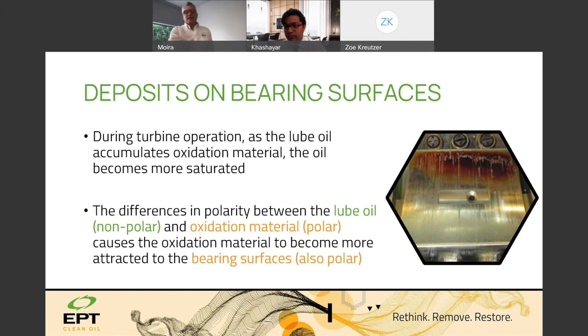When you see bearings with the varnish deposits on them, it is suggesting that the oil has been left in an unmanaged condition for an extended period, okay? And that's easily fixed and addressed nowadays. The oxidation material is polar in nature, which is based on where the electrons are spaced. And the base oils are non-polar, so you get a situation where the oxidation material is more attracted to the metal surfaces and mechanical components than it is to the oil itself. So that's why it's depositing at this point.